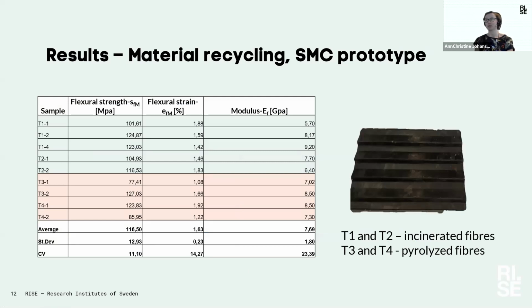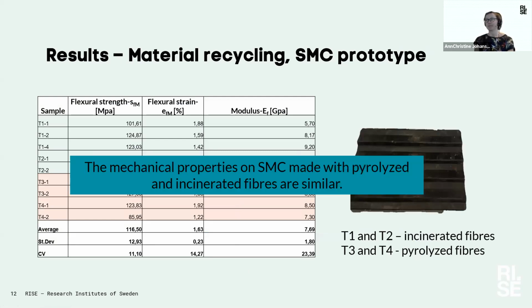And from these recycled fibers, we've also produced sheet molding compounds. And we have also tested that mechanically. And what we see is that the mechanical properties are more or less the same with both pyrolyzed and incinerated fibers.